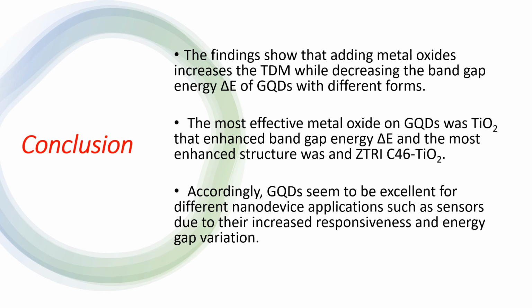So we can conclude our work that adding metal oxides increases the total dipole moment while decreasing the band gap energy of graphene quantum dots with different forms. The most effective metal oxide on graphene quantum dots was titanium dioxide, which enhanced band gap energy, and the most enhanced structure was graphene quantum dot zigzag triangle form with titanium dioxide nanoparticle. Accordingly, graphene quantum dots seem to be excellent for different nano device applications such as sensors due to their increased responsiveness and energy gap variation.